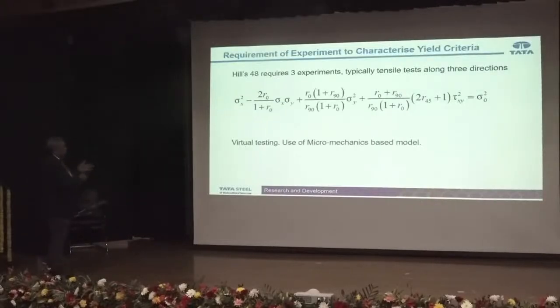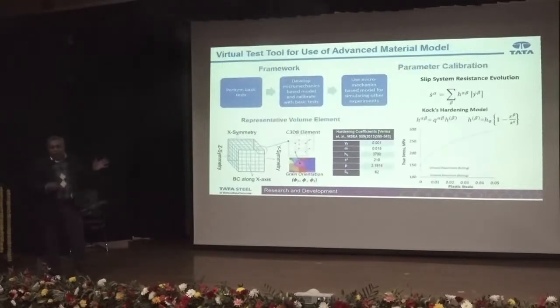So suppose we want to use this yield criteria, even the Hill's 48 yield criteria, we need to carry out 3 experiments, which is easy in this case because you just do the tensile test in 3 directions, 0, 45 and 90. But if you want to use Hill's 90 yield criteria or Barlat's yield criteria, you need to do equibiaxial test, etc., that facility is not there. So we came up with a concept where actually you can simulate this thing virtually.